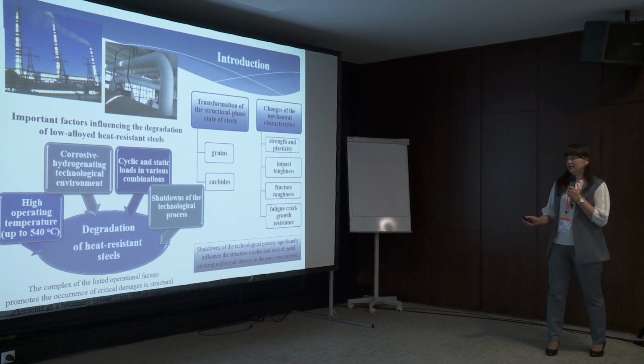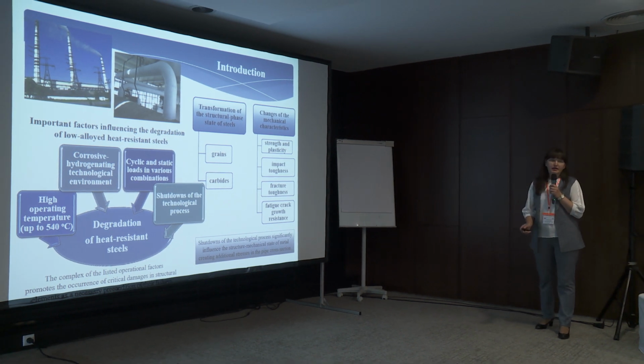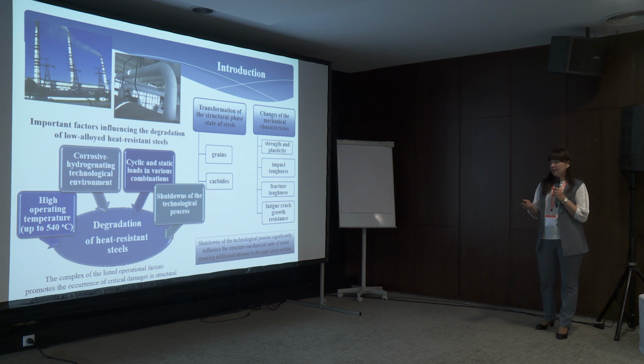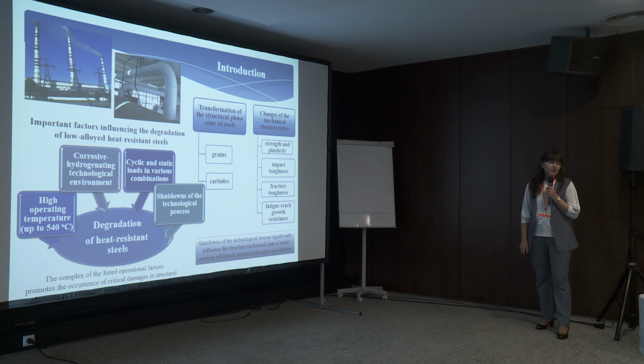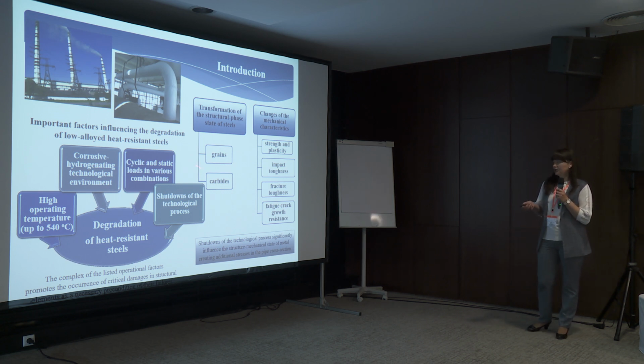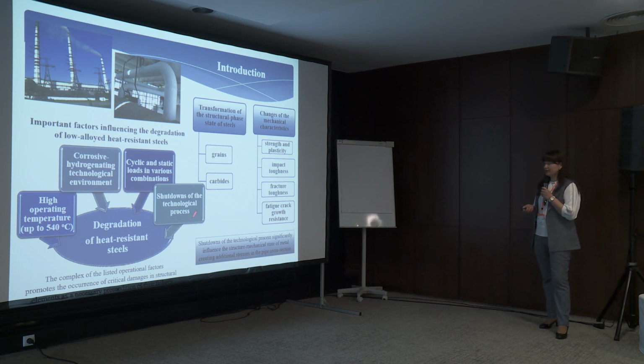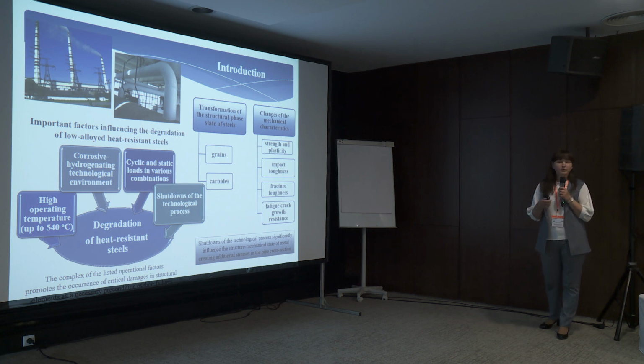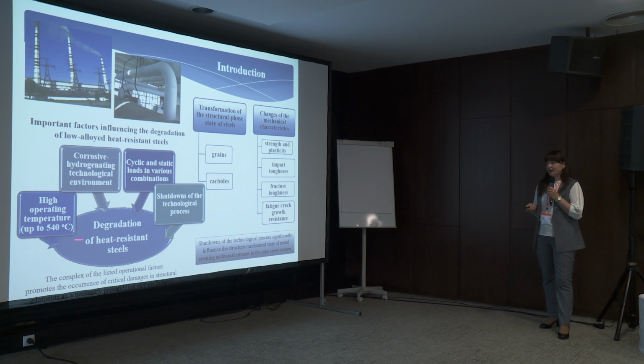Important factors influencing the degradation of low-alloyed heat-resistant steels of the main steam pipeline of the thermal power plant include high operation temperature, corrosive hydrogenated technological environment, cyclic and static loads in various combinations, and shutdowns of the technological process. The consequences of their impact are manifested by transformation of the structural phase of steels and change of the mechanical characteristics such as strength and plasticity, impact toughness, fracture toughness, and fatigue crack growth resistance. Shutdowns of the technological process significantly influence the structural mechanical state of the metal, creating additional stresses in the pipe cross-section. The complex of the listed operation factors promotes the occurrence of critical damages in the structural state.